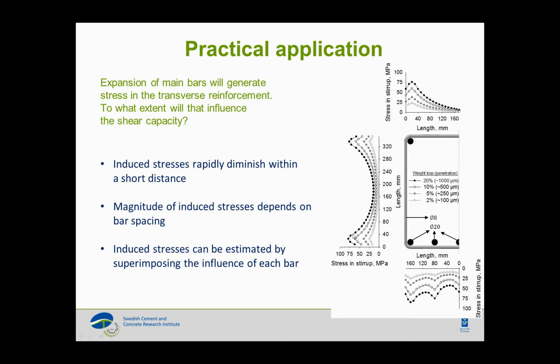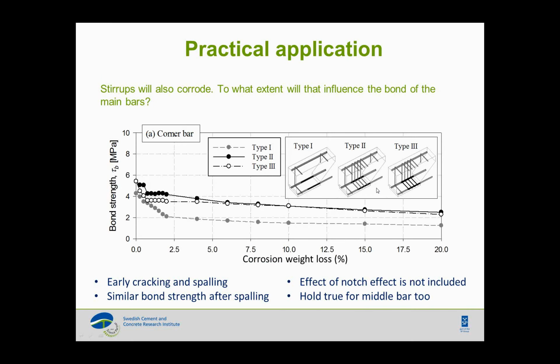Another question is to what extent the corrosion of a stirrup will influence the cracking pattern and the time to cracking. So we use this 3D detail model to look at different cases, to look at these specimens. Now we have type A, type 1, type 2, and type 3, the same thing as I described before. Now we are looking at bond strength versus corrosion weight loss. What we see is that in type A, where we have no stirrups, the bond strength drops very rapidly for even very small corrosion penetration, and then we continue with the same capacity, with the same strength.